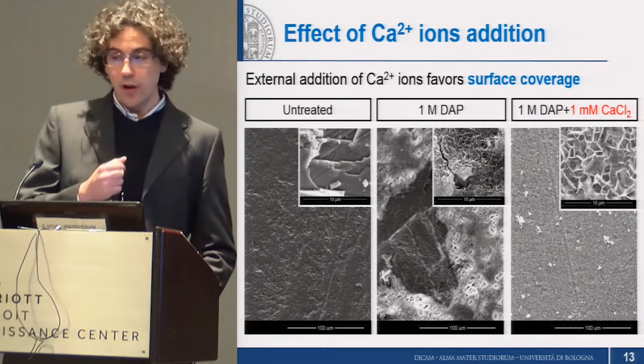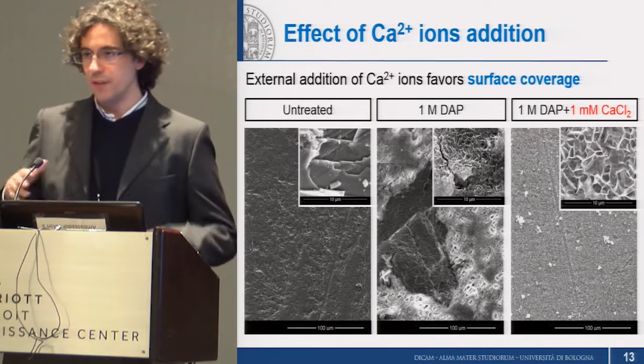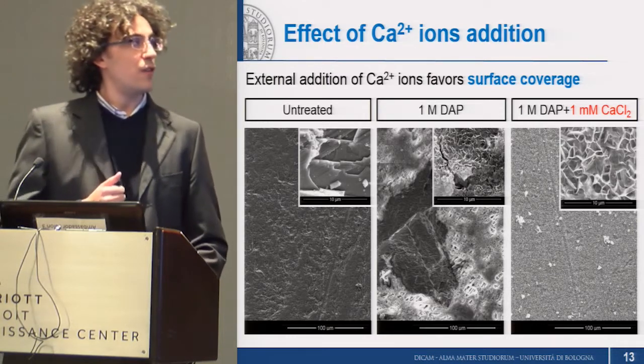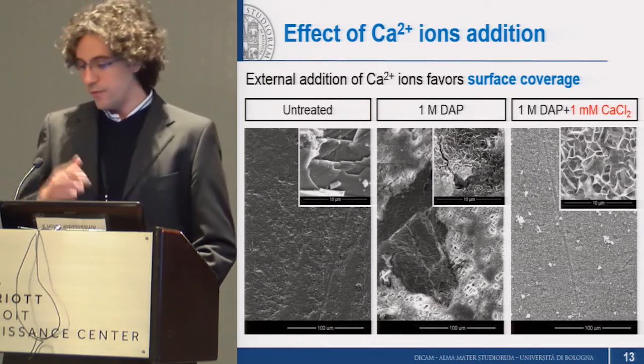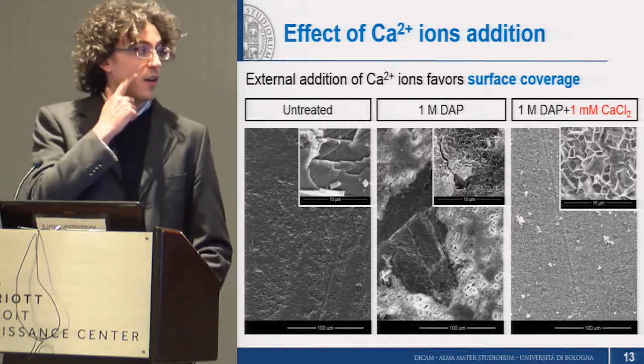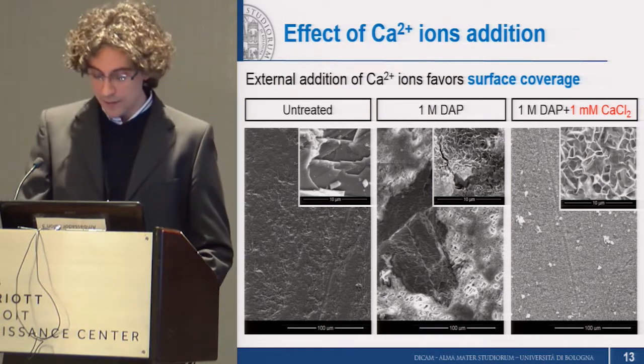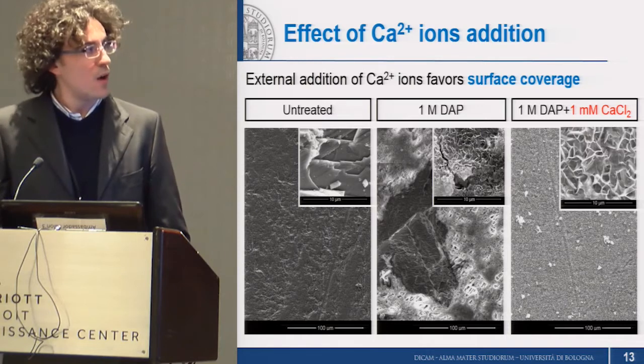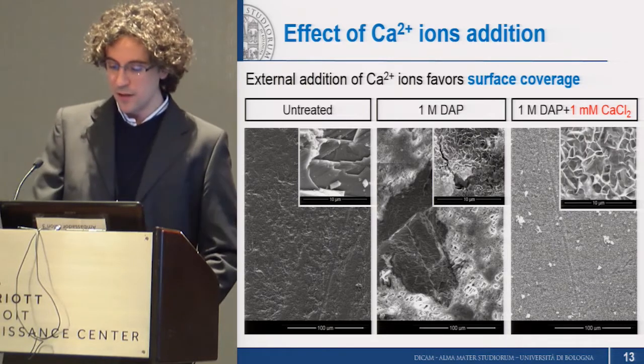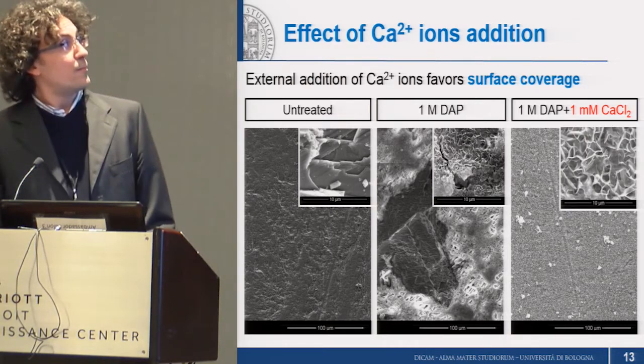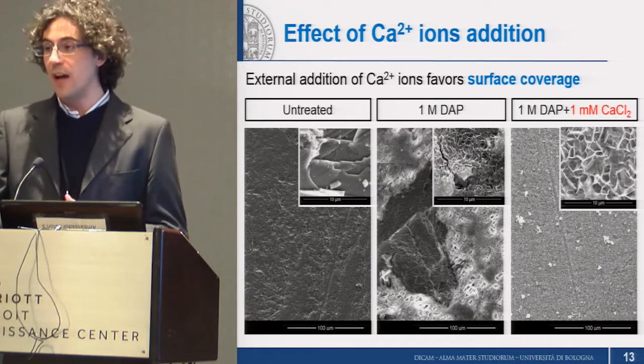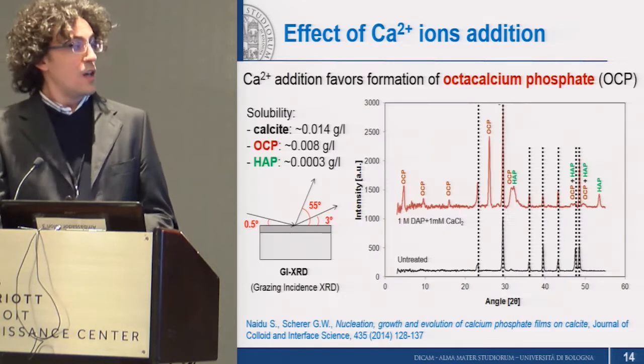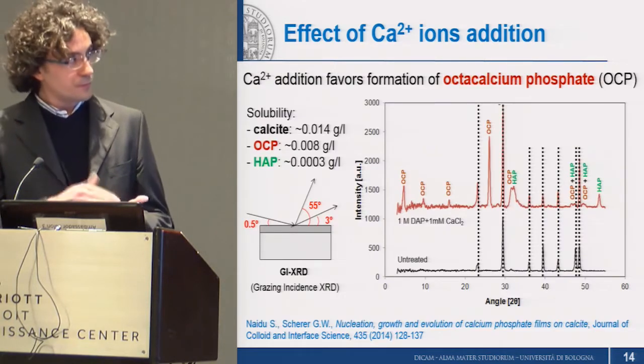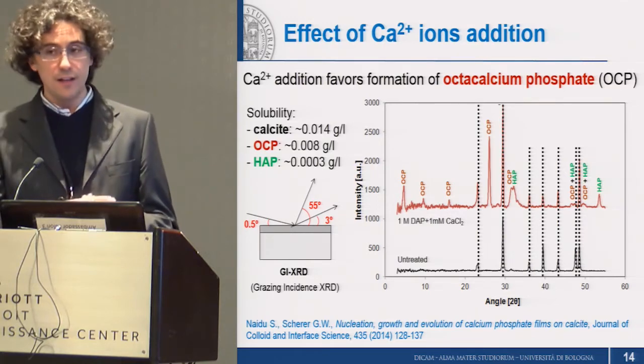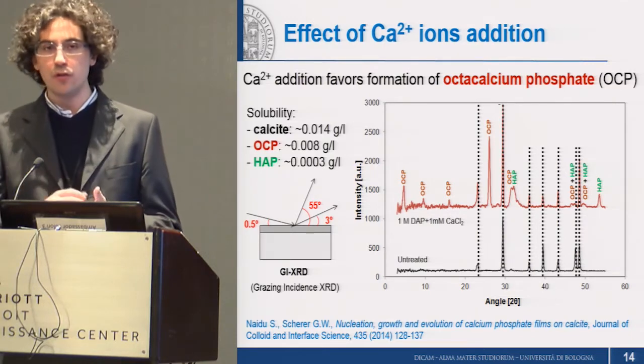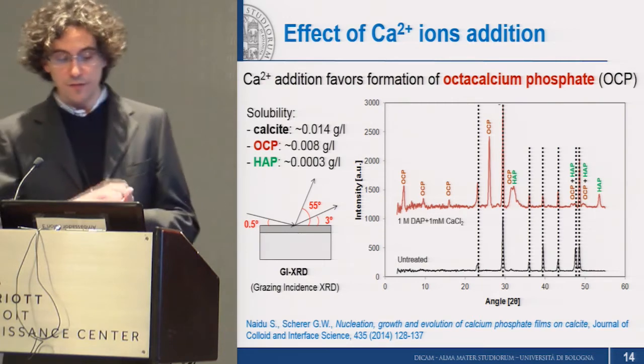Then also the nature of the calcium source to be added was investigated by screening between different salts, so for instance, calcium chloride, calcium hydroxide, and others, and in the end, calcium chloride was found to be the one providing the best results in terms of surface coverage. However, the addition of calcium ions into the solution also has an impact on the mineralogical composition of the new phases that form.